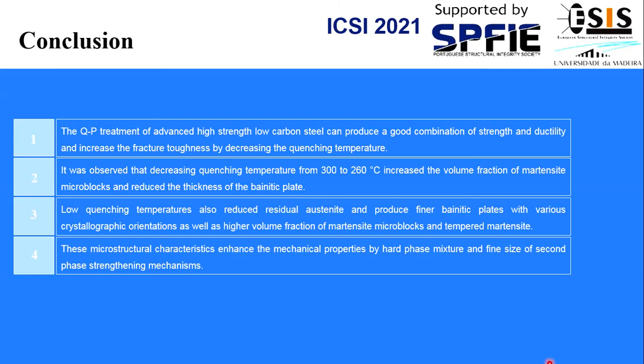Low quenching temperature also reduced residual austenite and produced finer bainitic plates with various crystallographic orientations as well as a higher volume fraction of martensite and tempered martensite. These microstructural characteristics enhance the mechanical properties by hard-phase mixture and fine size of second phase strengthening mechanism.